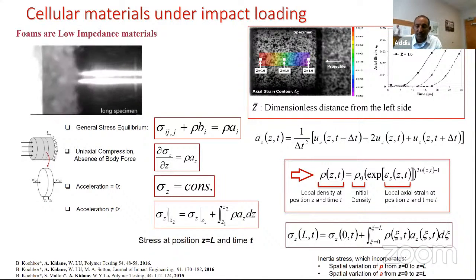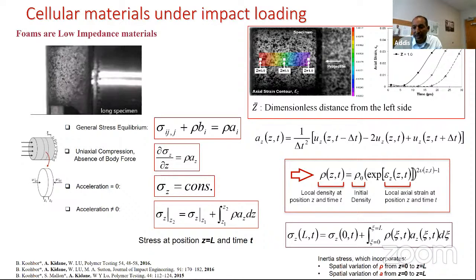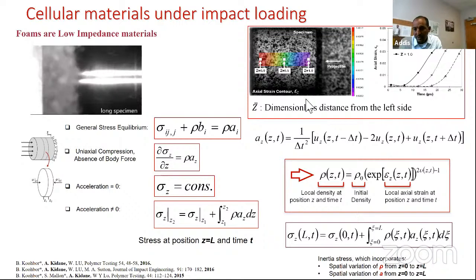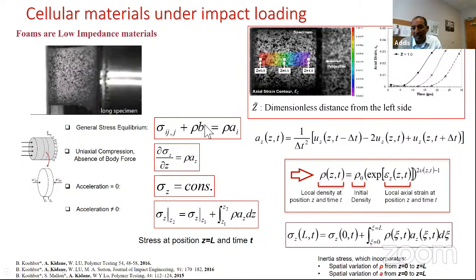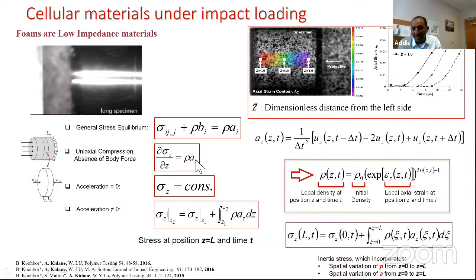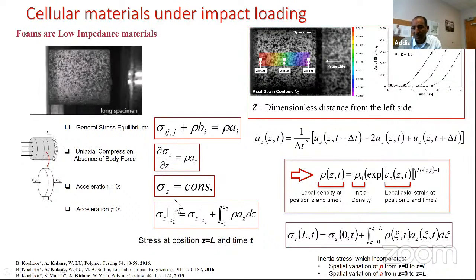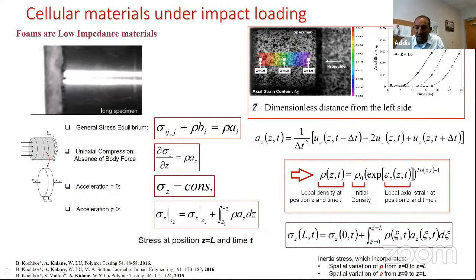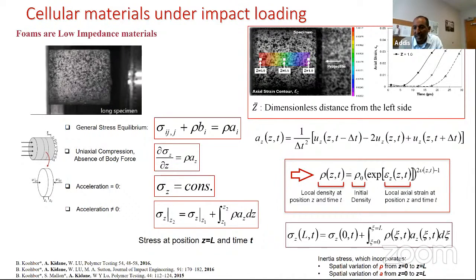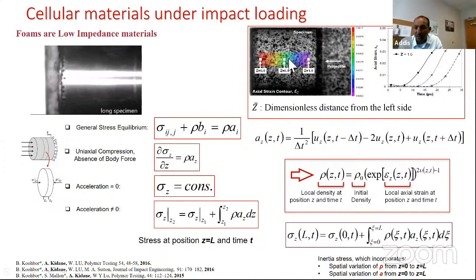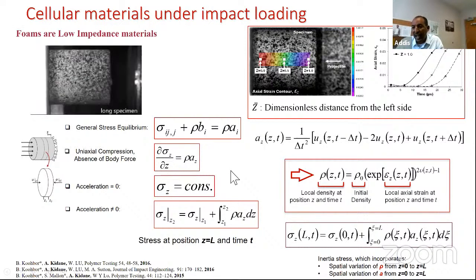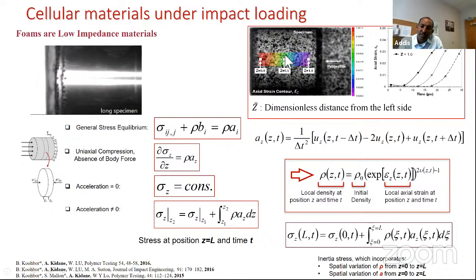So in our lab, we use digital image correlation to measure these deformations under different loading conditions. Rather than relying on quasi-static equilibrium conditions, we wrote the dynamic equations, including the inertia term. If it's uniaxial compression loading in the absence of body force, with acceleration zero in the quasi-static case, sigma z will be uniform. That means the stress is uniform along the specimen. If it's dynamic conditions, the stress at any position depends not only on the stress you measure on the backside, but also on the inertia terms. So having this inertia term is important if you want to measure the stress response of this material at high strain rate loadings. So we use digital image correlation to measure this.